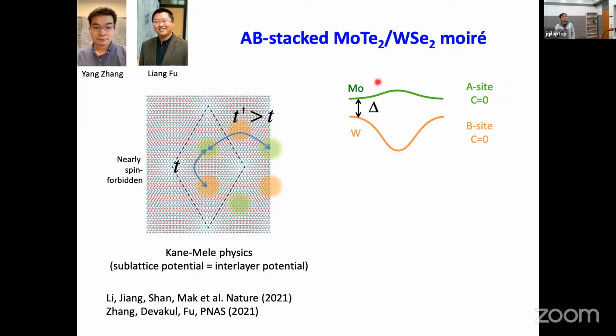Recently, this is the material that I will mostly focus on. I'll talk about all the different kinds of physics in just this one compound, which is AB stacked molybdenum ditelluride/tungsten diselenide. How we prepare this material is that we mechanically exfoliate two layers, and then we rotate 180 degrees and put them together. That's why we call it AB stacking, because we rotate them with a 180 degree stacking order. We make use of the lattice mismatch to produce a Moiré period of about 5 nanometers in this material. The low energy physics can be mapped to a two-band model because the topmost valence band of this entire heterobilayer comes from the molybdenum orbital, and the next valence band comes from the tungsten orbital.